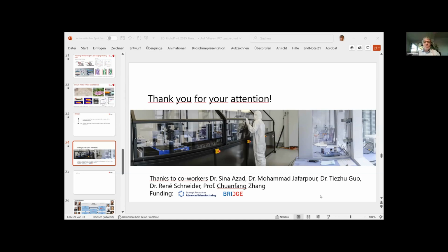Yeah, thank you. Very good point. So we did bending tests. If you look at the publication, we actually did 10,000 bending cycles of one of the substrates, and they performed extremely well. So that's a huge advantage over ITO actually. So they're very suited for printed and flexible electronics. But in this figure of merit, we cannot reach ITO. So actually, we are now developing a strategy to make a gravure printed silver grid and coat that with MXenes, and then you actually come very close to the numbers of ITO.